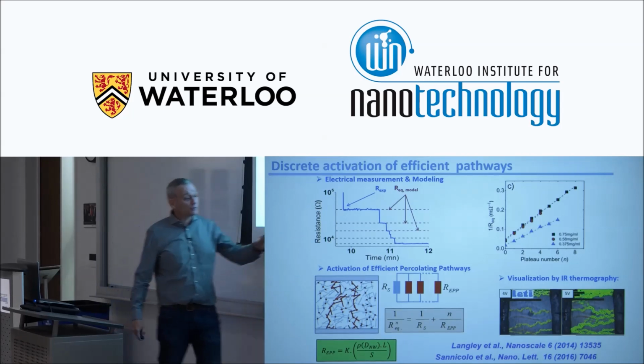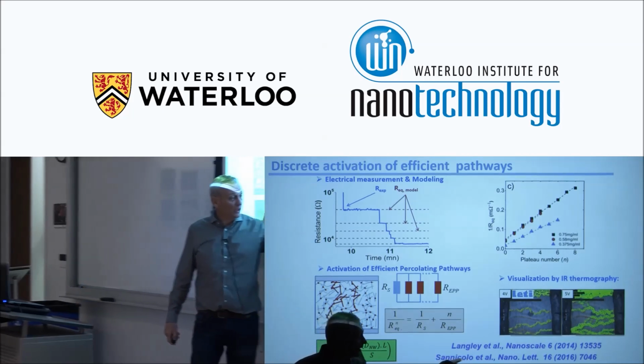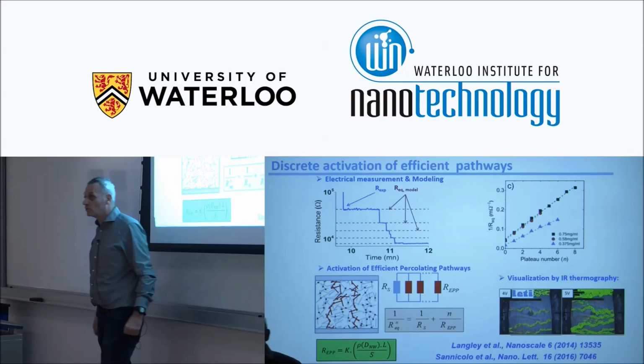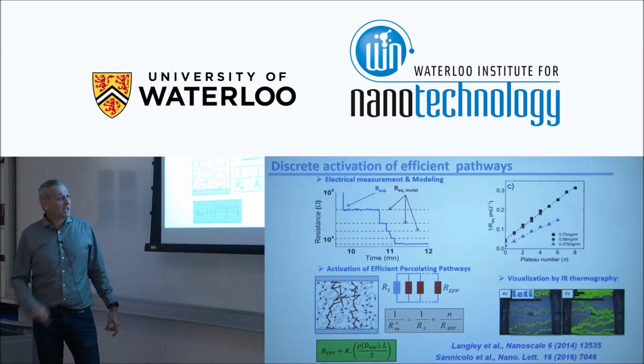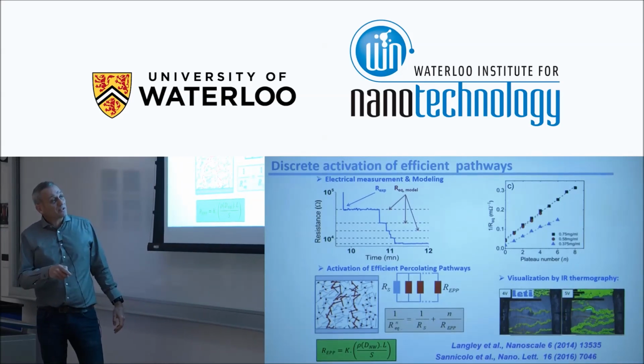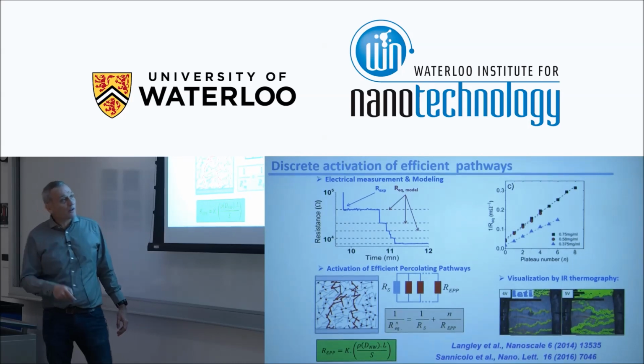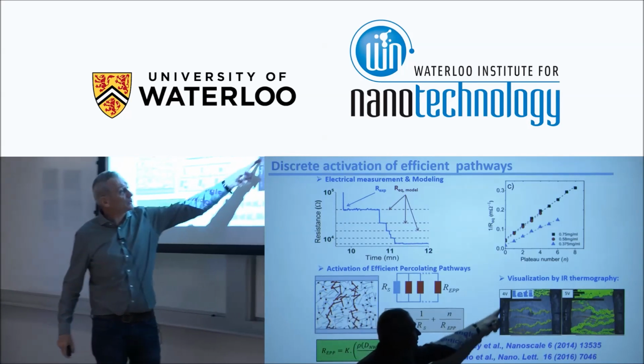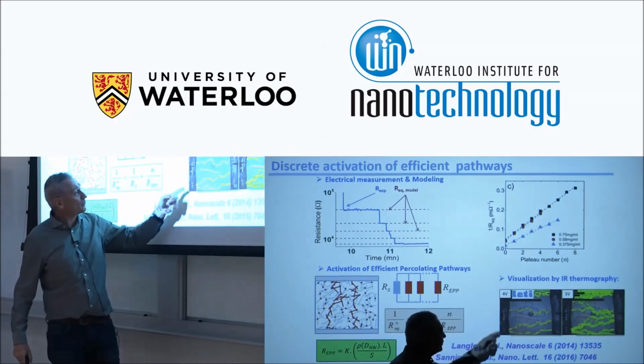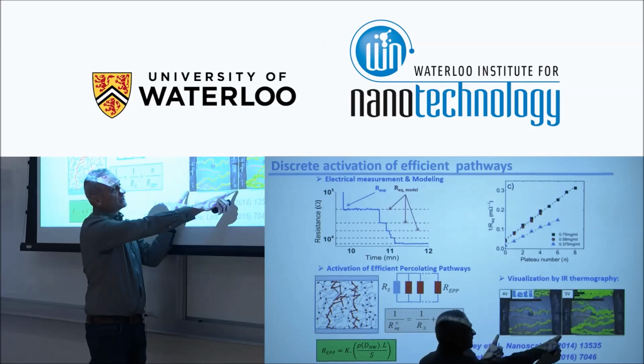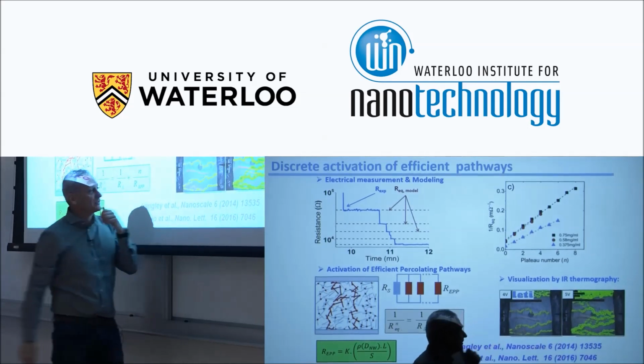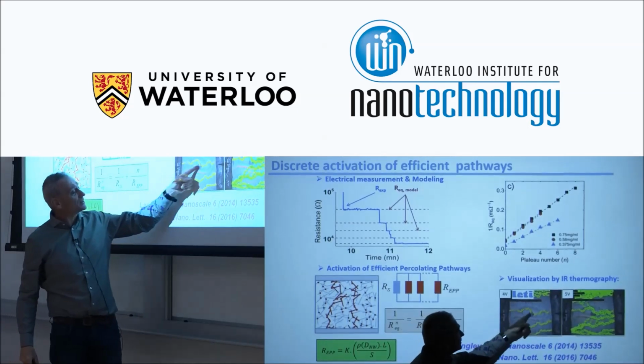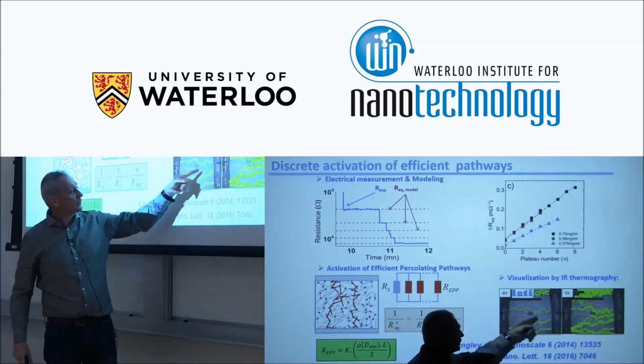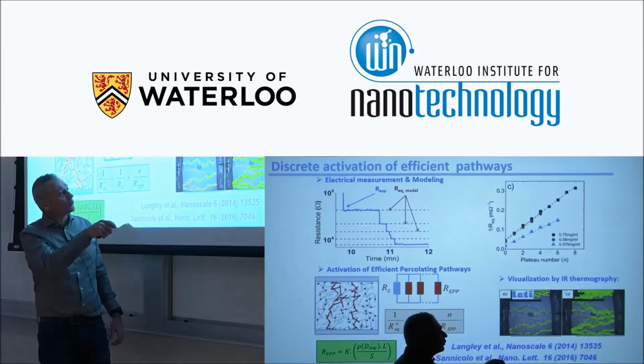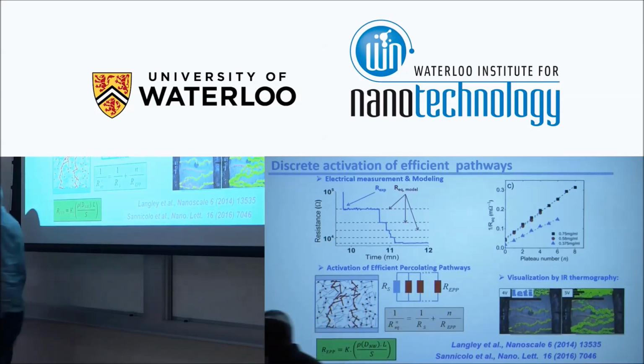and we had to wait 2 more years, during the PhD of Thomas Sannicolo, who is now a postdoc at MIT. And thanks to specific infrared thermography techniques, we were able to observe this. So there are 2 electrodes here. When we apply 4 volts, for example, and the length, between my 2 fingers, should be something like 6 or 7 millimeters, we can clearly see there are some efficient percolating pathways, thanks to the Joule heating effect. And if we apply 5 volts, for example, there are more and more of these percolating pathways.